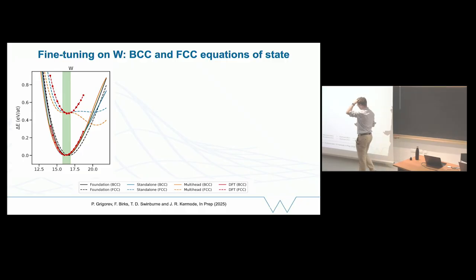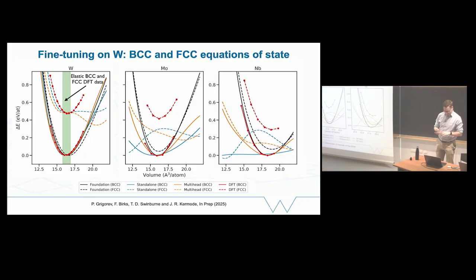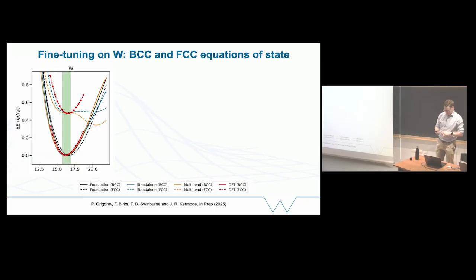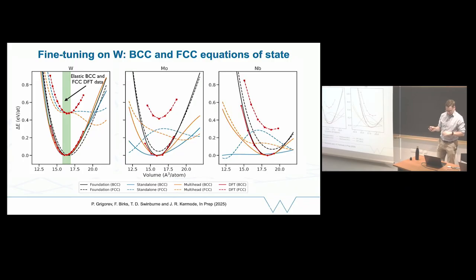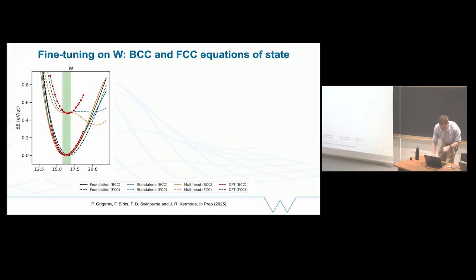Then I tried to fix this equation of state problem. And actually, this is a work in progress because I didn't do it in the smartest way, but I think it's got good lessons for a general audience. I added a little bit of data here in quite a narrow range of volumes. And of course, I fixed it there. But if you look at the multi-head fine-tuning FCC away from where I added data, it flops down again. So buyer beware. And in this case, there wasn't particularly good transferability to the other metals. It seems like it's messed up in some way.